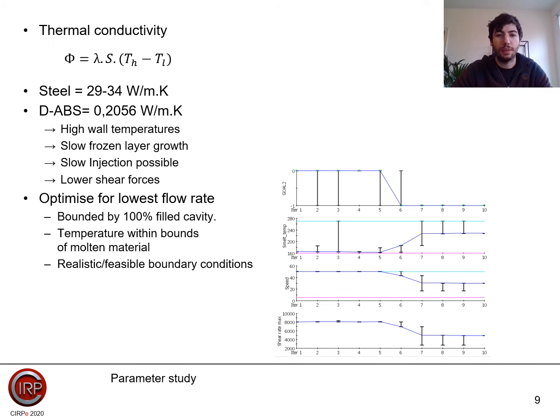Phi, the heat flux, is equal to the coefficient of thermal conductivity, in this case either 30 or 0.20, multiplied by the area of contact and the difference in temperature. The heat flux, upper temperature, and area of contact are assumed constant, so the difference in coefficient will make the temperature through the wall much higher. This will cause the frozen layer to grow slower, making it possible to inject at lower flow rate, which will result in lower shear forces.